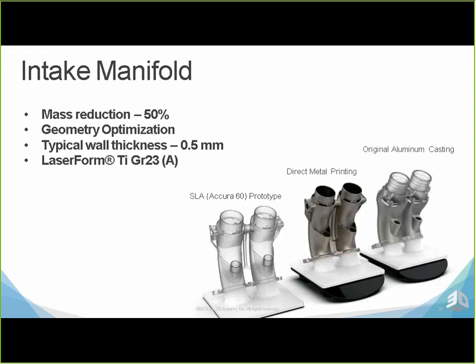So transitioning to direct metal printing, we're able to, A, optimize the geometry. Now we don't have to worry about fluid flow of the casting itself. And B, really minimize that wall thickness down to what's necessary as opposed to what's necessary for castings. This allowed us to go down to even a half millimeter wall thickness using titanium and get an overall mass reduction of 50%. So this really hits it all. As you'll find when you're optimizing these structures, especially if you started with aluminum and you're transitioning to a more advanced metal, you'll find that you need significantly less metal to meet your design size. A tremendous amount of what your engineering organizations are used to is designing for the process. So what we encourage people to do is to rethink that design for process and focus on designing for 3D printing for applications like this. Next.